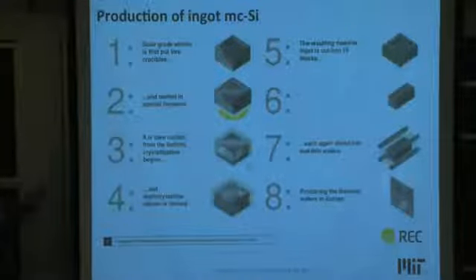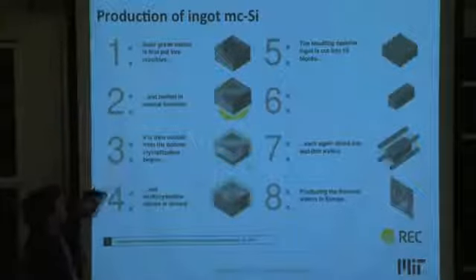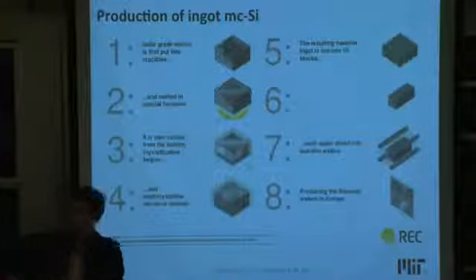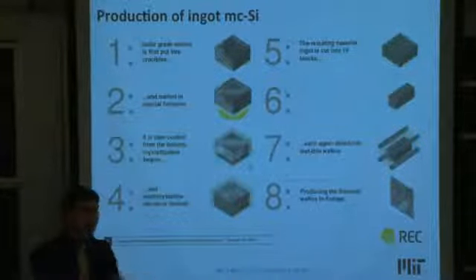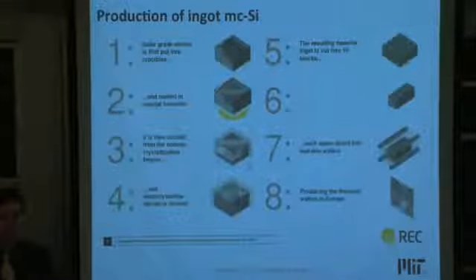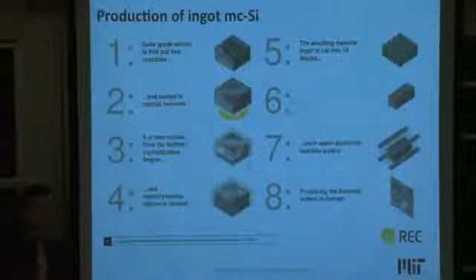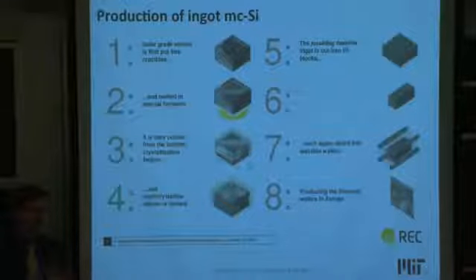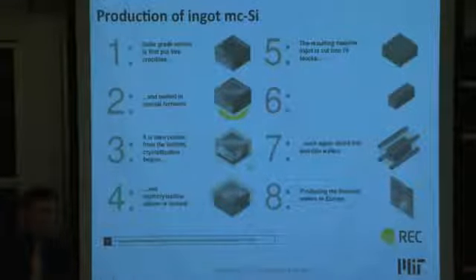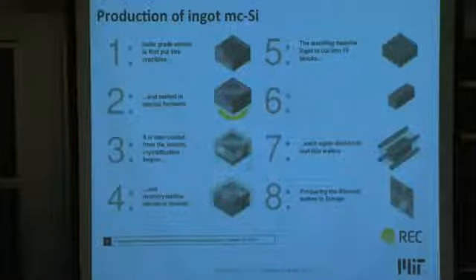Again, you would start with the solar-grade silicon. That could either be coming from the Siemens process, or it could be coming from the fluidized bed reactor, or it could be coming from an upgraded metallurgical grade silicon, the liquid purification route. But somehow, some way, you get chunks or granules of silicon that have a high enough purity for you to make solar cells out of. And high enough purity is typically on the order of 1 part per million impurity content.